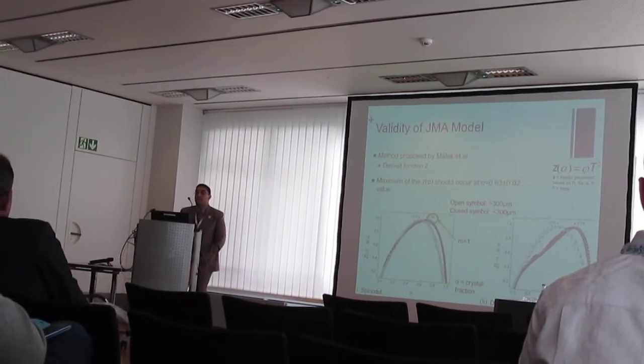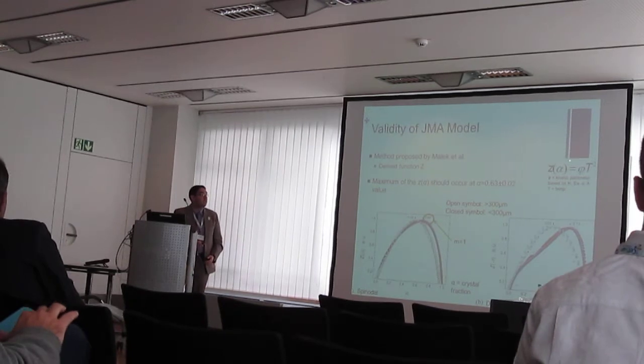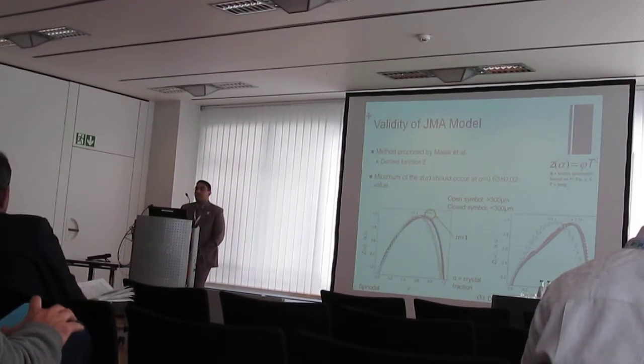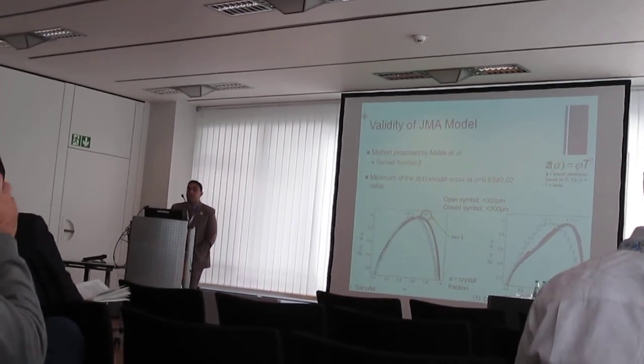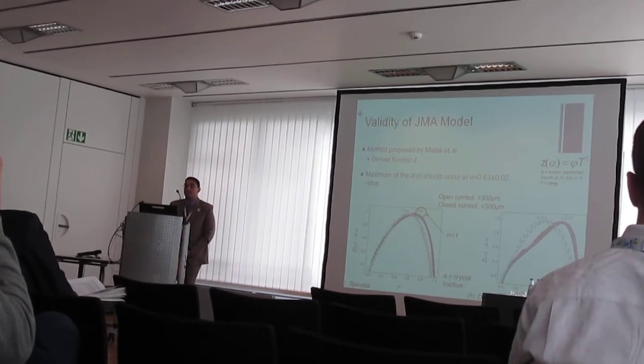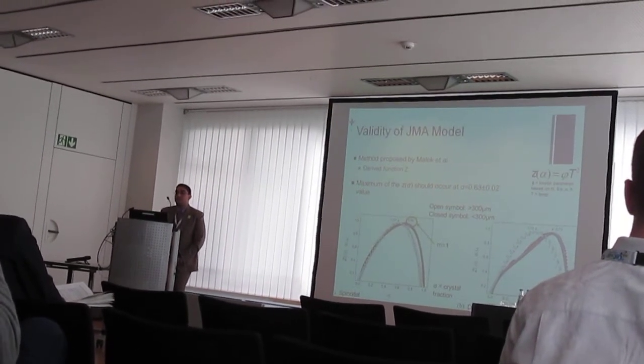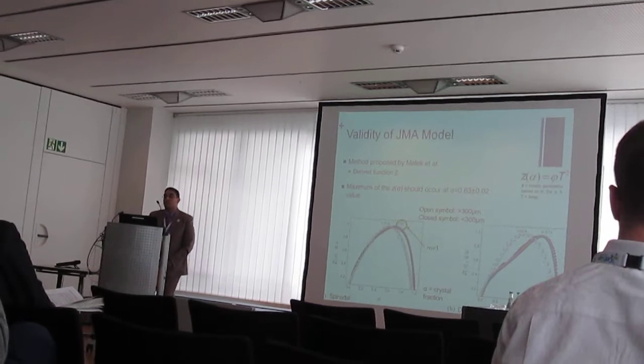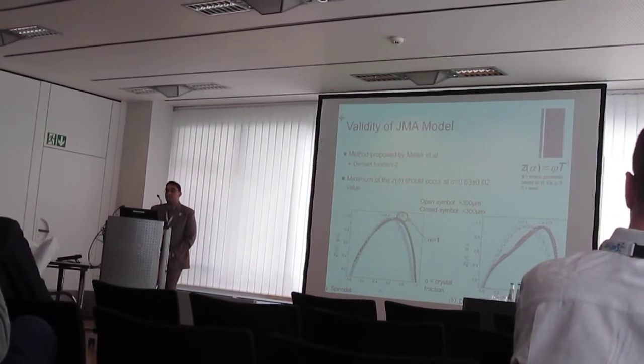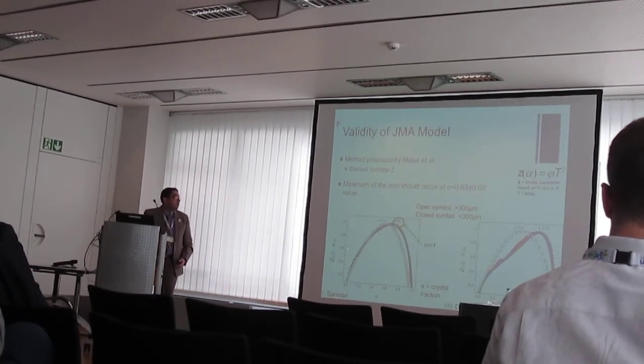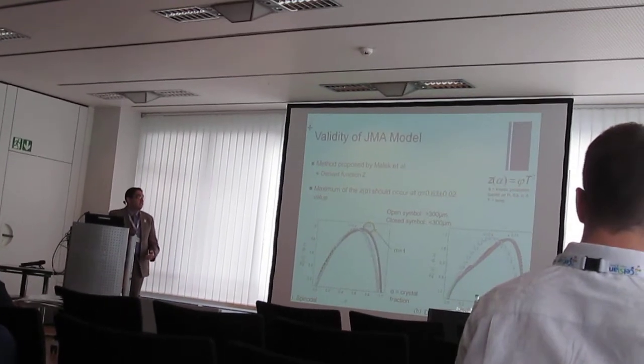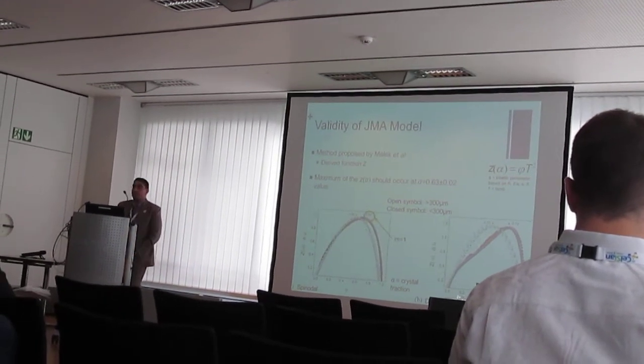Malek derived this function z, which is a function of kinetic parameters and temperature. He said that the maximum of the z of alpha curve should occur at alpha equals 0.63 plus or minus 0.02. So we did exactly that when we determined the z of alpha curves for the different particle sizes for our bioglass.